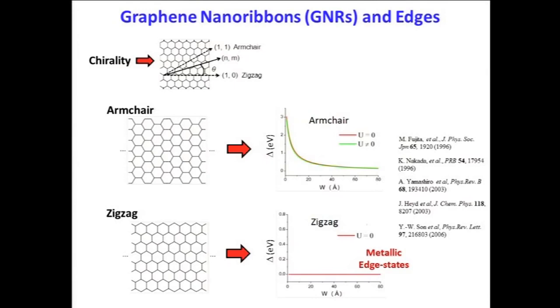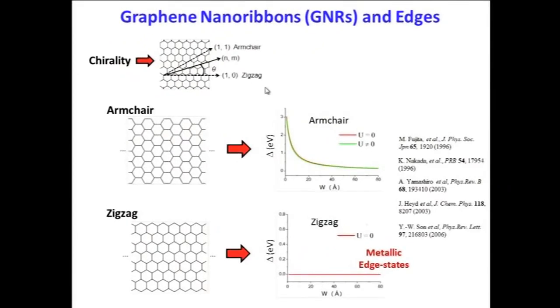On the other hand, if you take graphene and if you cut it at this other angle, 30 degrees from the armchair angle, right here at that angle, then you get what is known as a zigzag nanoribbon, where these edges are zigzag edges. And the zigzag nanoribbons have been predicted to have very different behavior from the armchair nanoribbons. For example, in the absence of electron-electron interactions, it was predicted a while ago that you should get one-dimensional metallic bands that are localized at the edge states. And since these edge states are metallic, it was initially predicted that you should not even get an energy gap for a zigzag nanoribbon.